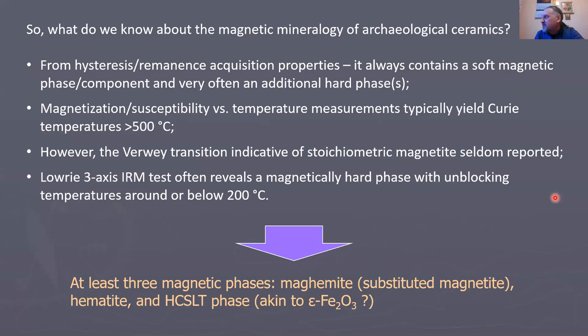Instead of the usual single-mineral ferrimagnetic samples, we have to deal with at least three magnetic phases: maghemite, hematite, and also this HCSLT phase, all mixed in various proportions depending on the sample.